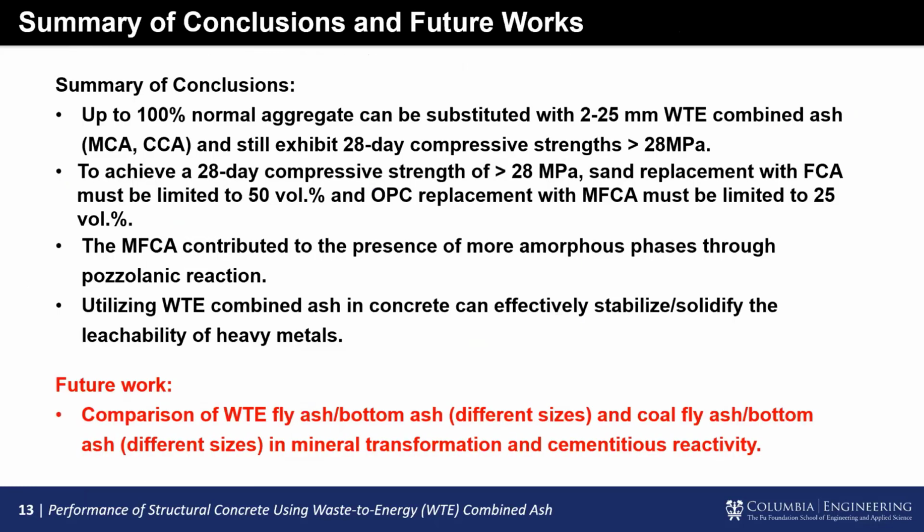Let's see the conclusion. So first of all, up to 100% of the stone aggregate can be substituted by the combined ash in the size range of 2 to 25 millimeters, and the concrete products exhibit a 28-day compressive strength larger than 28 megapascals, comparable to commercial concrete.